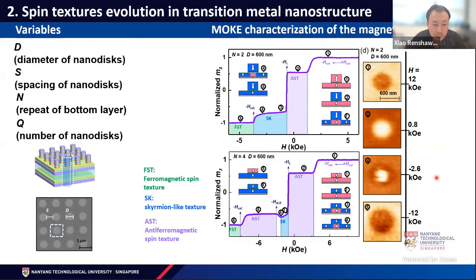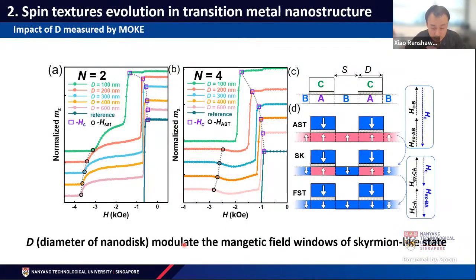Next, beyond the N, we also play with the diameter. For example, we change the diameter of the nanodot from 100 nanometers to 600 nanometers. Obviously, the diameter can help us modulate the window of the magnetic field that enables us to nucleate the skyrmion-like state. It's true both for N equals 2 and for N equals 4.